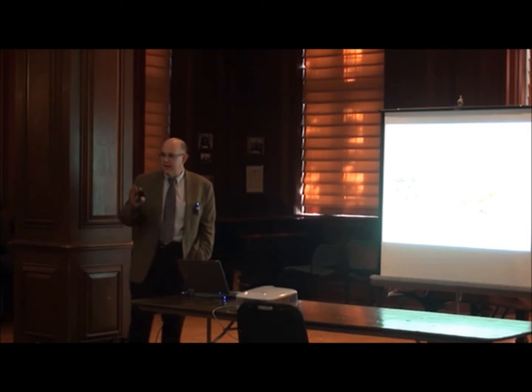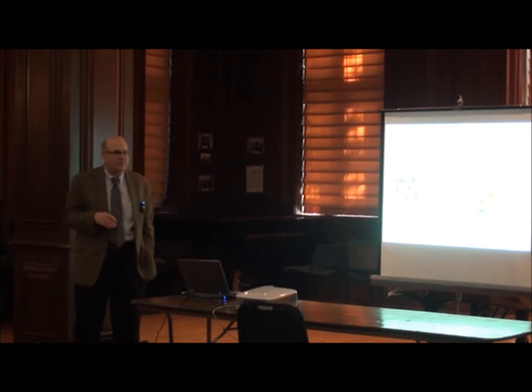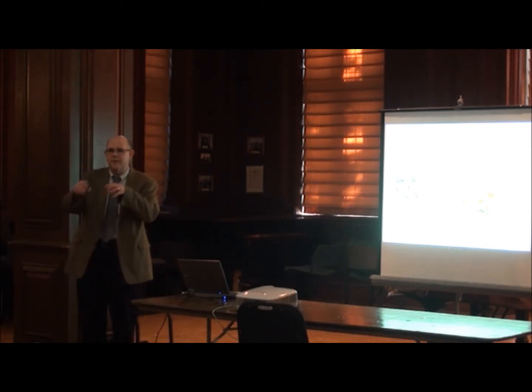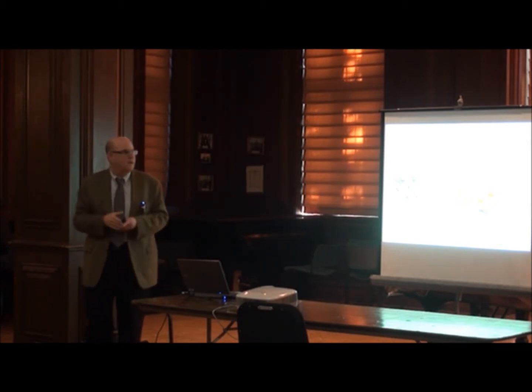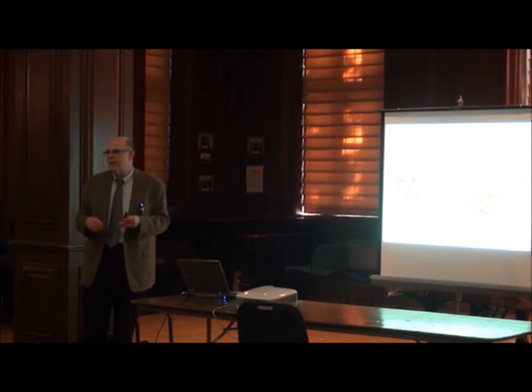Also, the pressure that each one pushes back with, and again, I'm under elastic deformation here, is also somewhat independent of the force. The only thing that's really dependent upon the force is the number of asperities that I'm interacting with. And that's where this whole concept's coming from. So as I push down, I get more and more asperities supporting the load. More asperities gives me larger real area of contact, so I get a higher friction. But each little asperity is on average the same size, independent of force, and the force each one pushes up with is independent of force.